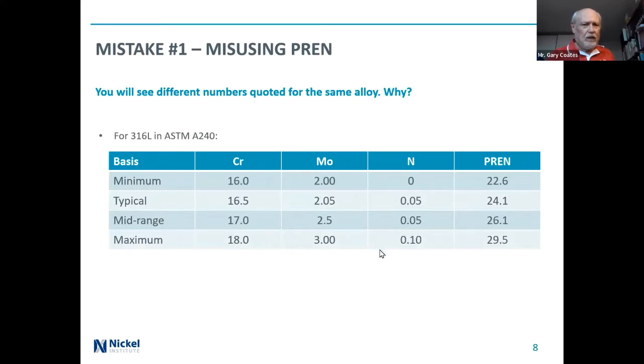And this is just showing the minimum chromium content, the minimum molybdenum, minimum nitrogen content for 316L. And then we calculate the PREN numbers, and you can see they vary tremendously. If you use just the minimum alloy content, you get a number like 22.6. If you use the maximum content, you get 29.5. Typically, it might be 24.1, and that's the number I tend to use, or 24, just as a round, 24.5, something in that area I tend to use.